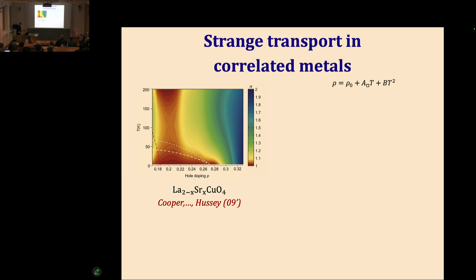If you measure at zero field, it would look like this, which just drops to zero. You measure at higher field, it would extend to lower temperature and then drop to zero. But if you want to measure all the way down to the lowest temperature, you'll need some threshold field, and that varies. It's a good question. The resistivity in the normal state is a little bit field dependent, but let's just think about this as the resistivity as a function of temperature and doping at 30 Tesla. It's some fixed field. It might look like this.